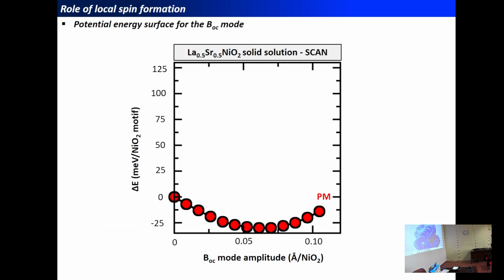Okay. And just to finish, I want to insist on the role of the local spin formation there, which is sometimes neglected in the literature, notably in some papers that ruled out the existence of an electron-phonon coupling in these nickelates. So for instance, if we look at the potential energy surface associated with the breathing distortion, we start from the undistorted cell and we add some displacement associated with this type of distortion. And we do that in the half-doped system where we expect to have the disproportionation effects.